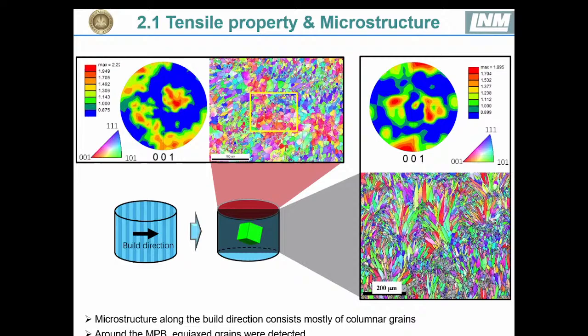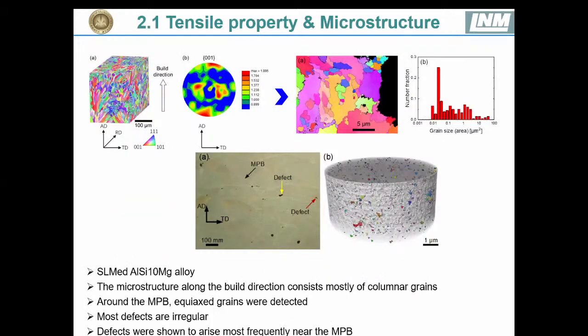And in the other direction, we can see this equiaxed grains, which is formed quite uniformly. And also we can see a texture of 001 is formed due to this solidification of this process. And the microstructure is further observed.